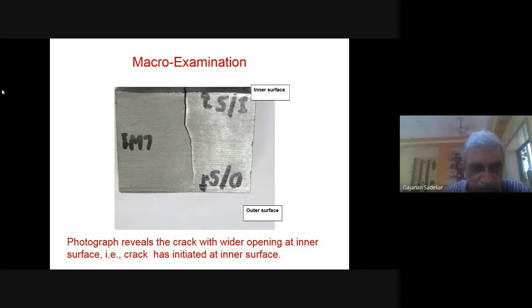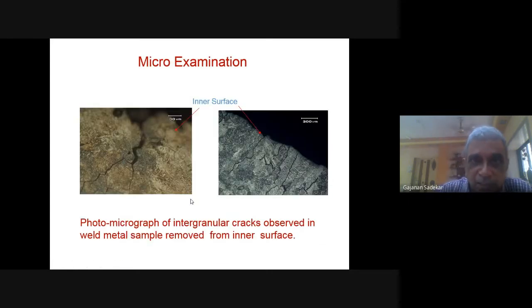Then macro examination. You look at this macro examination. The photograph reveals the crack with a wider opening at the inner surface. Inner surface, the wider opening. And slowly as it goes out, the opening was reducing. This means the crack initiated from the inner surface. Then micro examination of it. Photomicrograph of intergranular cracks observed in the weld metal sample. Look at these cracks. They are intergranular cracks and they are branching. Lot of branching of the cracks, right?